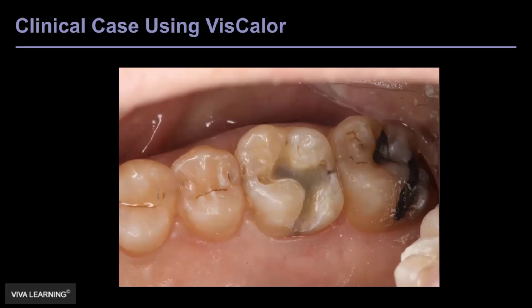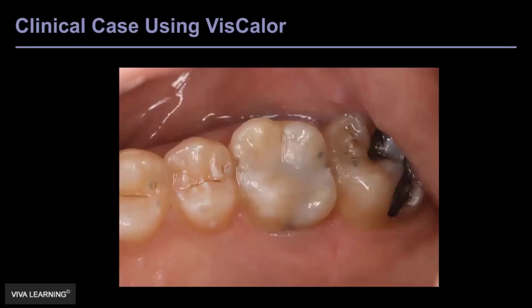Now, the nice thing about the VisCalor composite is the way it's designed: as you heat it up, it really behaves more like a flowable. It adapts very beautifully at 155 degrees. But as you allow it to sit for just a few minutes, the VisCalor bulk firms up and becomes very sculptable. So in a very short amount of time, I'm able to place this material in, carve it with my instruments and light cure it, with very, very little adjustment to do post-operatively.